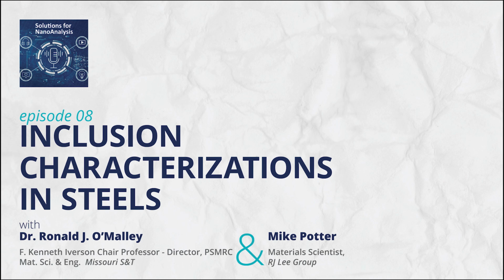Though now as the electron microscopy is getting better with field emission microscopes and things like that, we're starting to push those boundaries. You're dealing with ultra clean steels. So now, the steels are stronger and thinner. So the size limits of what are considered possible inclusions that could cause some deleterious effects have now changed, and they're getting smaller as well because the steels are getting thinner. And so we're starting to look at things in the submicron down into the nano inclusions. And I think some of these tools now available, as they get better, will potentially open up a whole new world of understandings of inclusion formation and characterization.